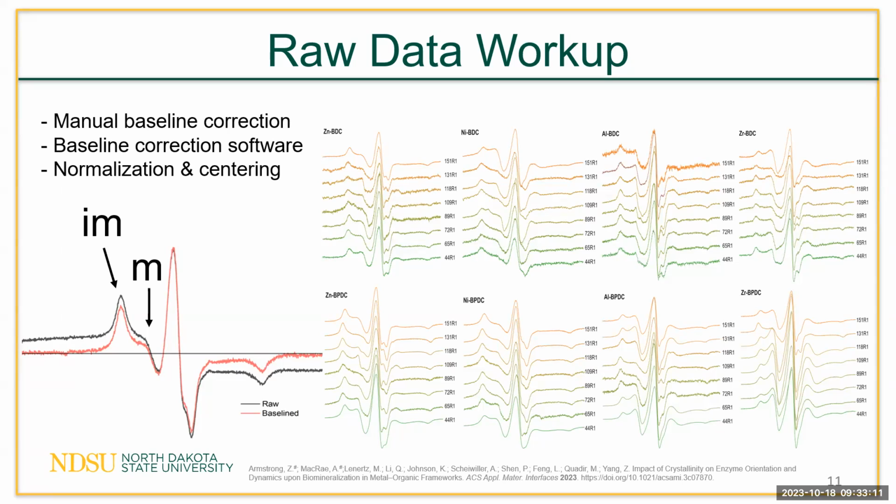Also, depending on the confinement of the protein, it actually could be more or less stable based off the framework stability. So really, it depends on what your application is. If you're working in organic solvents that are pretty harsh for proteins and would normally denature a protein, maybe we want a more stable MOF to keep it from unfolding and denaturing in that solution, in which case the confinement could actually help to make sure that it stays in its active conformation.